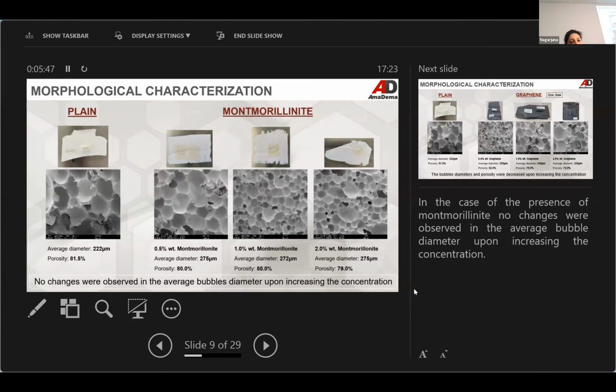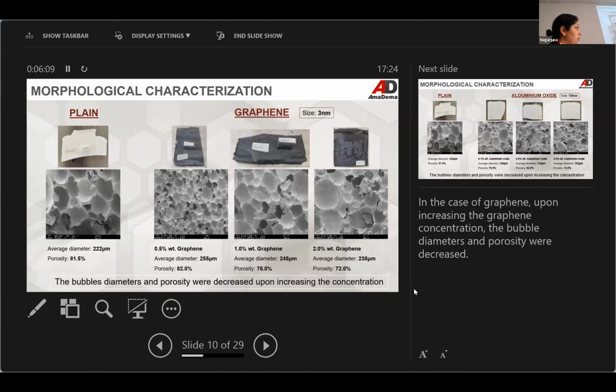Now, montmorillonite nanoparticles had a very different effect. We haven't seen a significant change in the morphological properties. As you can see, the average diameters measured were very similar. The porosity, as expected, is also very similar. And finally, when we use the graphene nanoparticles, keep in mind that these are very, very small nanoparticles compared to the previous particles we've checked. The bubble diameters appear to decrease when we increase the concentration of these nanoparticles.